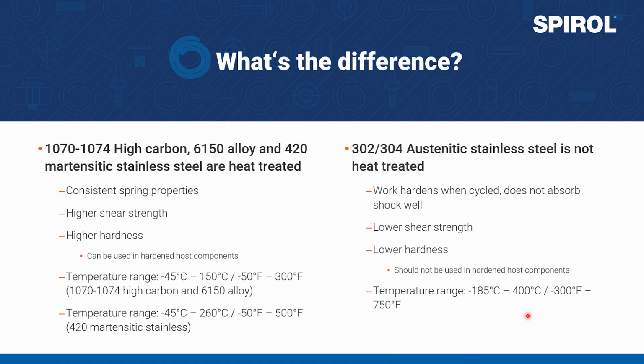As high temperatures do not significantly affect this material's mechanical properties, it can be used in a wider range of temperatures than our hardened materials. And the effective range for this material is -185 Celsius to 400 Celsius, or -300 Fahrenheit to 750 degrees Fahrenheit.